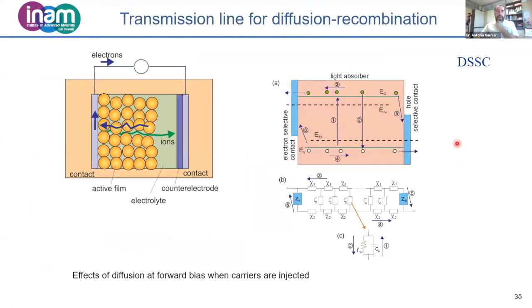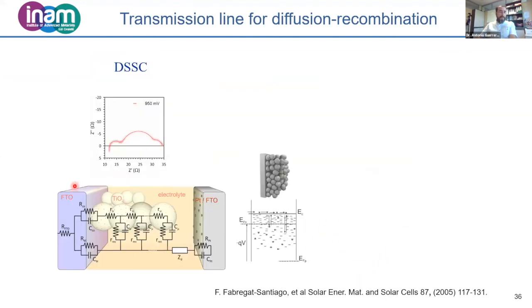Okay, so moving now to a different example. For a long time, our group has been working with dye-sensitized solar cells. In these solar cells, we have titanium dioxide semiconductors, some contacts, and ionic electrolyte dissolved in liquid, typically. And in this system, the general equivalent circuit model was well established, and it was very often observed the signature of diffusion of carriers. I will not go into the details, but the system was very well understood, and it was clear what was the meaning of each of the arcs.